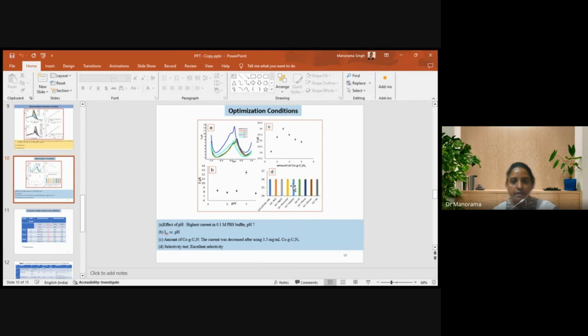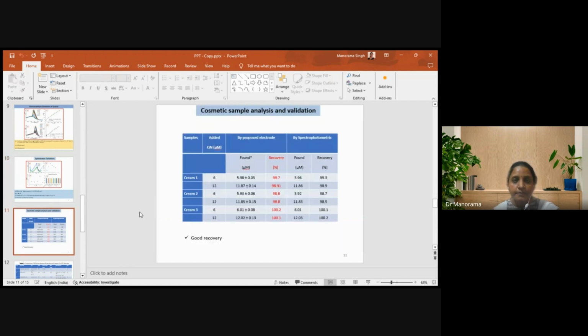Different interferences which may be present in the sample, like resorcinol, catechol, citric acid, phenol, glucose, dopamine, magnesium chloride, sodium chloride. So we found that there is negligible effect of other interferences that may be present in the system.